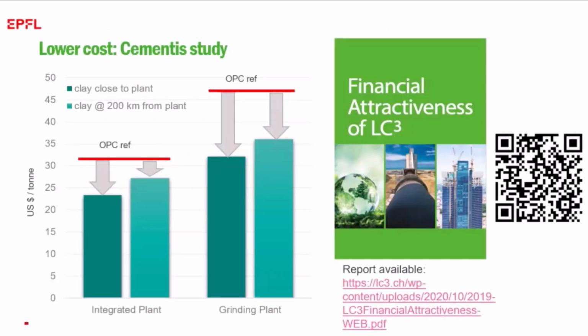So we're always hearing about green premium. We're always hearing that these new products cost more to make than the existing ones. But this study here, we evaluated it very closely, and even up to 200 kilometers from a plant, even if you have to bring your clay that far, you can, in an integrated plant where you're also producing clinker, have reductions of like 10, even 20%. In a grinding plant, which is the situation in most of Africa where you have to import clinker, you can have much bigger savings. And this study was done a couple of years ago before the energy crisis. As energy prices go up, these differences will increase.